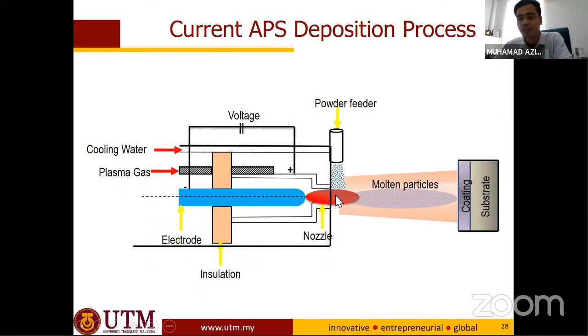So they will push the powder to the substrate. When they push here, it becomes molten. The powder becomes molten and then is deposited on the substrate. Because of the temperature gradients between the molten material and the substrate, you will see a formation of the porous structure of the ceramic.